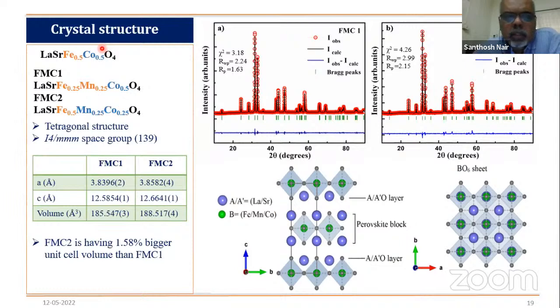So what we did was slightly engineer the system and incorporate manganese into it, because we know the manganese-cobalt interaction generally ends up giving a bit of ferromagnetism. So we have 2 different compositions, either cobalt-rich or iron-rich, and then see what happens. We are able to make a single phase of the system. You can also see from the composition that you have 3 different ions, so you have a complex magnetism, because iron-manganese can interact, manganese-cobalt can interact, iron-cobalt can interact. So it's a complex system.